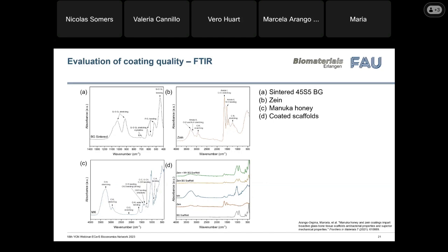So on the right, on the lower part, we can see the different scaffolds: the scaffold with zein, the scaffold with zein and honey, and also the glass scaffold. And then we could detect that at around 3,200 wave number, we have the peak characteristic of the honey. So we realized through this method also that the honey was present in our scaffold.